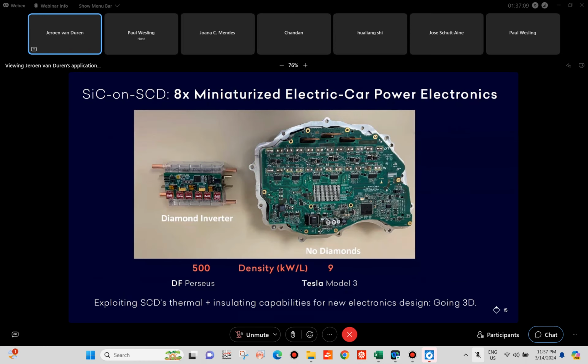Finally, to give you a sense of what we're doing in power electronics, what you see here on the right is the traction inverter from a Tesla Model 3, which is the state of the art. And on the left, you see our traction inverter that's based on diamond, taking advantage of the thermal conductivity and electrical insulation of the diamond. And where the power switches are silicon carbide. Now, thanks to the properties of diamond, you can now completely redesign the traction inverter so that you get a traction inverter that's 8 times smaller than the state-of-the-art traction inverter today in the Tesla Model 3. And you can see that the power density is 500 kilowatts per liter compared to 9 for the state-of-the-art traction inverter.